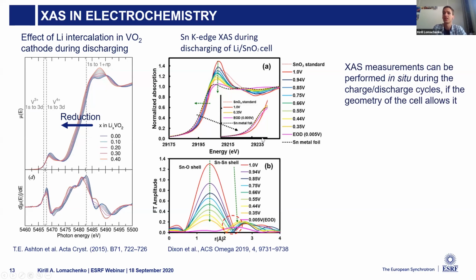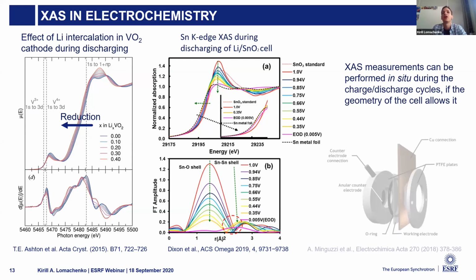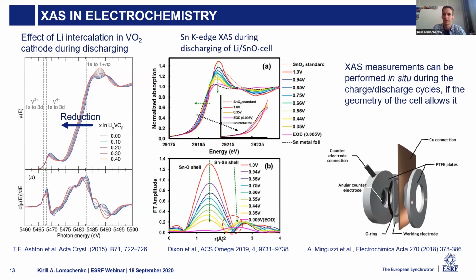So we can do in situ measurements, but of course the electrochemical cell and also the catalytic cell should be compatible with the limitations of the technique. The geometry basically has to be compatible, also the thickness of the sample should be compatible, and the amount of the species of interest should be compatible with the XAS measurement. But the tolerance is pretty large, so these measurements are pretty much doable.